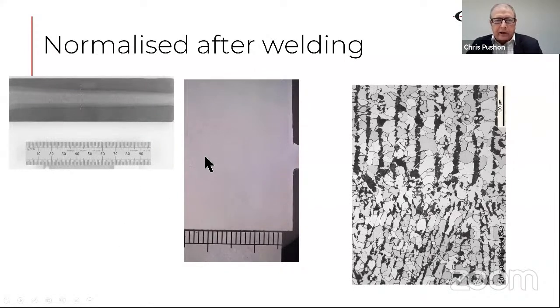This is another illustration of the benefit of not adding a welding consumable. So what you see here is about 125 millimeter thickness. This is the weld metal, you see, and the heat affected zone. This is in the as welded condition, but if you carry out a full normalizing heat treatment after welding, the weld becomes invisible. And the reason for that is this is the weld metal here. You get a very fine grained ferritic microstructure with distributed pearlite. In the parent metal, you get banding and a lot more inclusions. So one of the benefits of welding with this process is inclusion number reduces and the size of inclusion reduces. So that's a benefit. In fact, in this case, if you normalize, the weld properties are better than the parent metal properties.